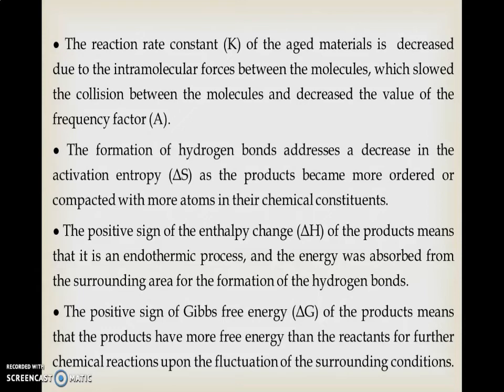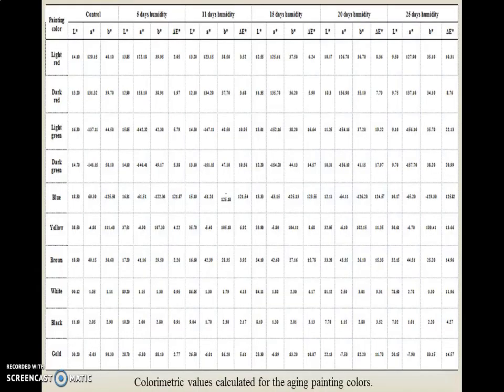So, the non-spontaneous reactions need more energy for the chemical interactions, and the humid conditions can provide more water molecules in the deterioration process of the painting. Also, the colorimetric measurements showed there is a decrease in the brightness index L star with an increase of the color difference delta E, with darkness of the paint film and weak photostability. The humidity drives the color change in the painting.